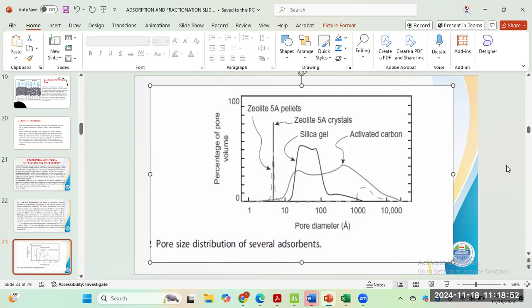Thank you, ma. Contributions, please. Hello, ma. Yes, go on. So from the graph, as we can see, zeolite has a high percentage pore volume, which means that its rate of adsorption is very high, but its pore diameter is very low, which means that effectively the amount of adsorbate it can absorb is small compared to silica gel, which has a relatively high percentage pore volume, which means that its rate of absorption is also high, and its pore diameter is large, showing that it can absorb a large amount of adsorbate. While the activated carbon has a relatively small percentage pore volume, which means that its rate of absorption is lower than the others, but it has the highest pore diameter, which shows that it can hold the highest amount of adsorbate here.